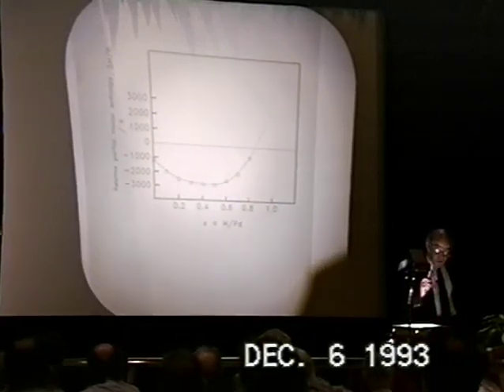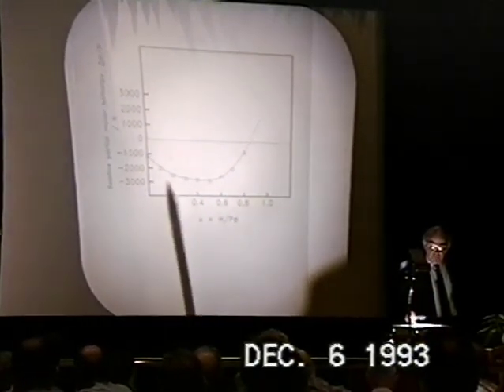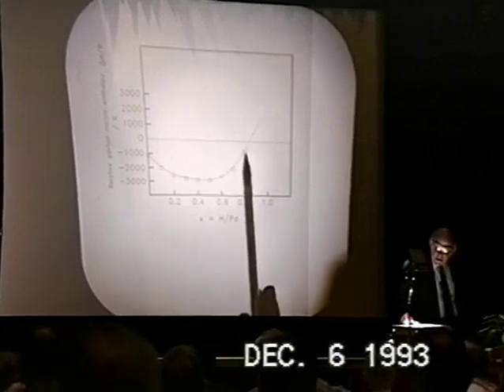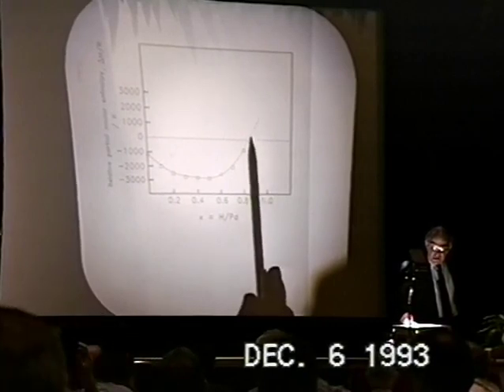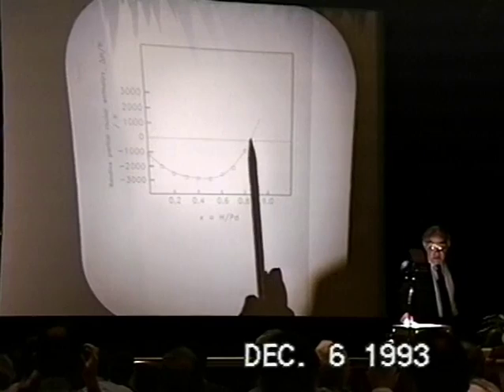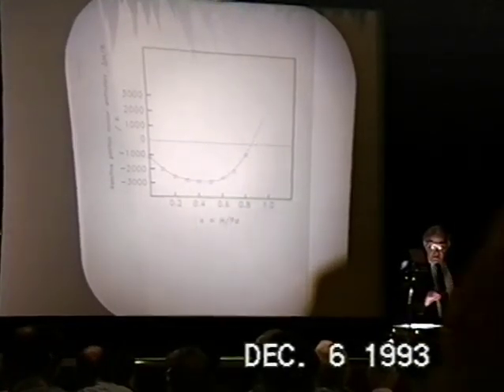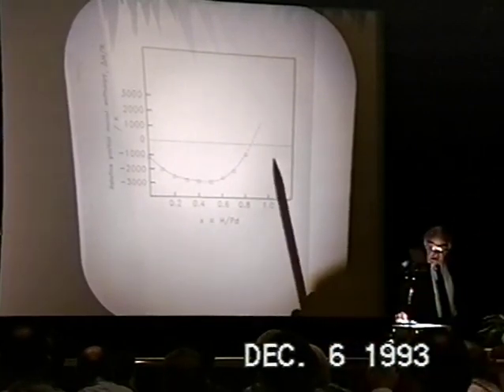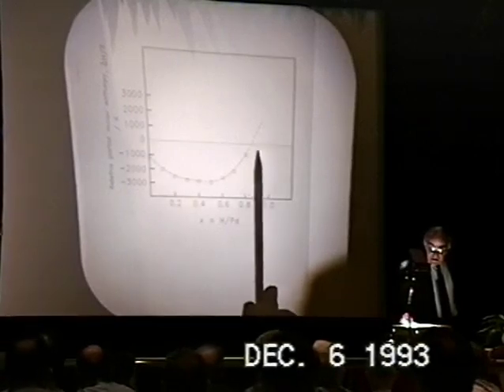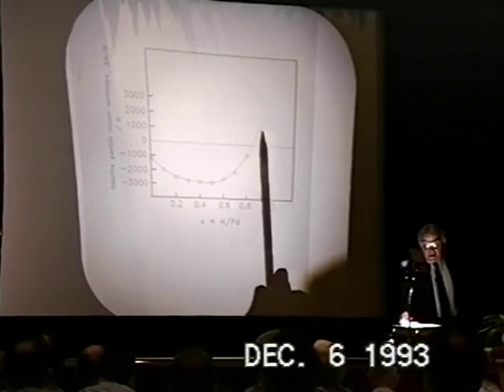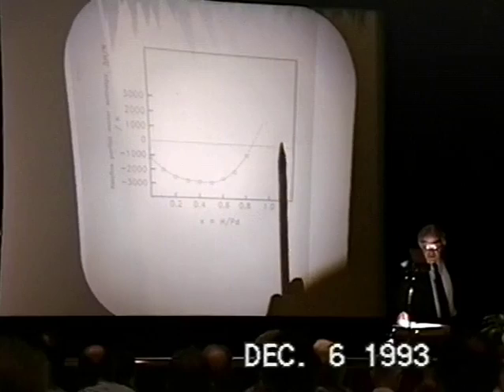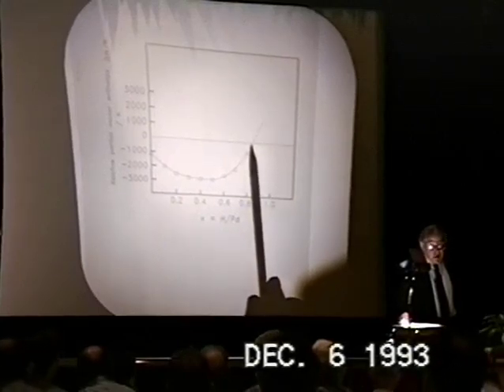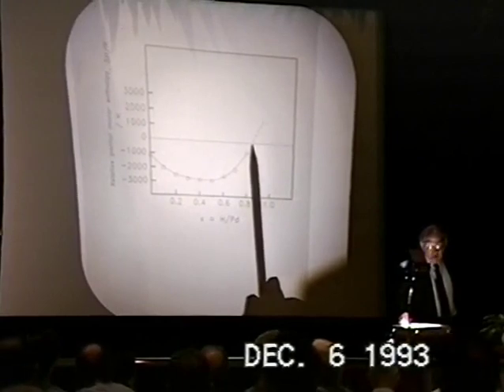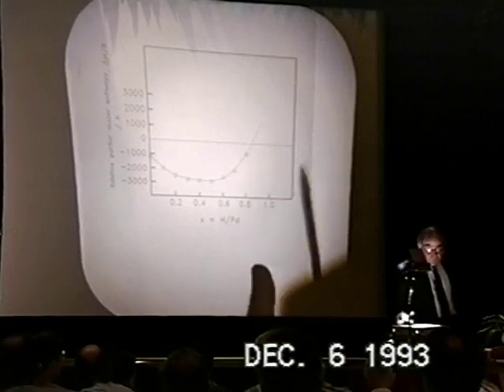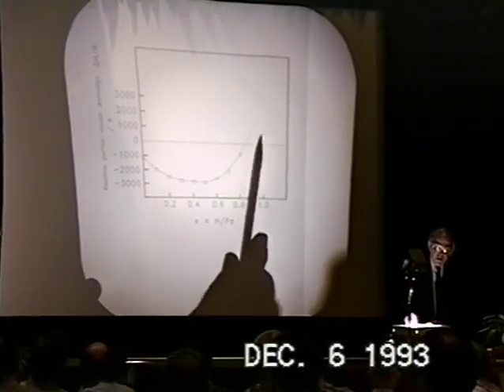One possible answer is that the dissolution of deuterium or hydrogen in palladium is exothermic, but if we increase the loading ratio, then we would predict that above a certain loading ratio, the dissolution becomes endothermic. Now this is a very important point to our design, the protocol which is designed into our experiments. And of course, as Mike will no doubt say later, other people will say as well, emphasize that you get excess energy generation when you get high loading ratios. So this transition here, which may be simply a consequence of the change in the entropy of dissolution, or may actually involve the formation of a third phase, you have to go through that at a sufficient speed in order to achieve the